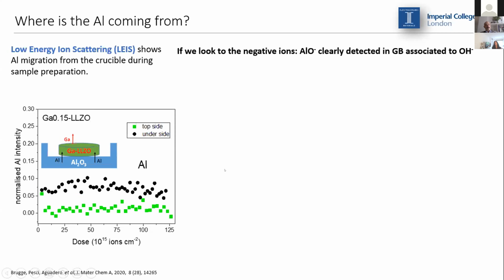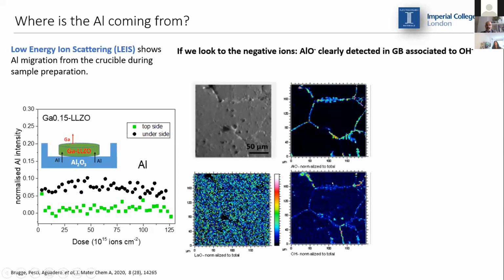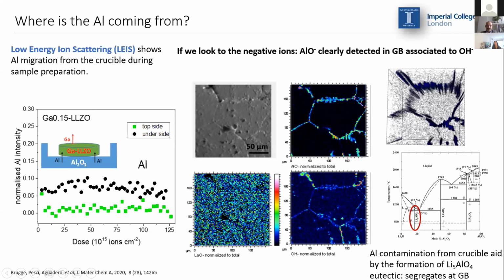lower content of aluminium compared to the side that was actually in contact with the alumina crucible. So we know now where the aluminium comes from, and if we look at the negative ions, so if we follow aluminium oxide and OH, we can actually clearly see that there is a segregation of these alumina species at the grain boundaries. If we look at the phase diagram of lithium and aluminium, we can notice that we can have a favorable formation of this phase, lithium-5 aluminium oxygen 4 eutectic, at a temperature very similar to the temperature that we use to sinter our pellets. So it could actually be a problem.